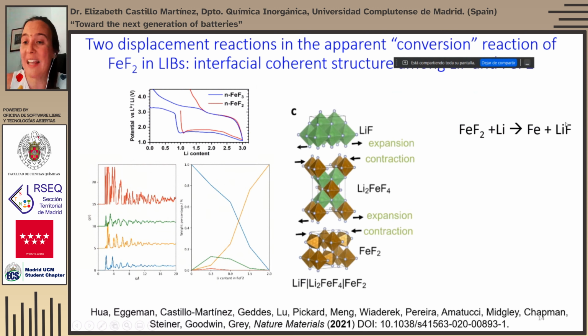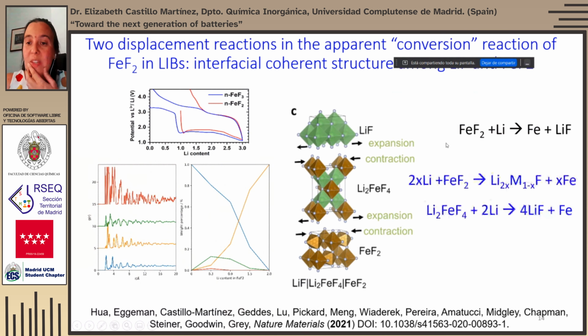So instead of explaining this reactivity with a one-step conversion reaction, we could explain this reaction as a two-step displacement reaction where lithium ions displace iron from the sublattice, and then the insertion of further lithium ions again completely extrude the total amount of iron.